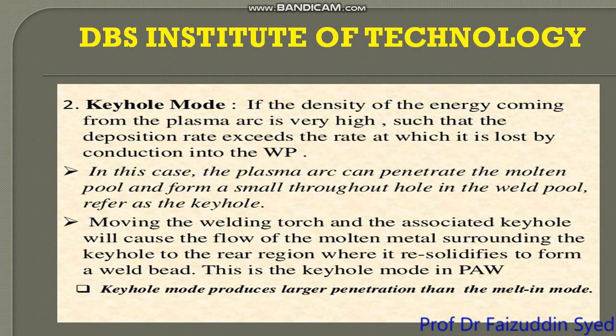Number two, the keyhole mode process. If the density of the energy coming from the plasma arc is very high, such that the deposition rate exceeds the rate at which it is lost by conduction into the workpiece, in this case the plasma arc can penetrate the molten pool and form a small through hole in the weld pool. It is referred to as a keyhole. Moving the welding torch and the associated keyhole will cause the flow of the molten metal surrounding the keyhole to the rear region where it resolidifies to form a weld bead. This is the keyhole mode in plasma arc welding. Keyhole mode produces larger penetration than the melt-in mode.